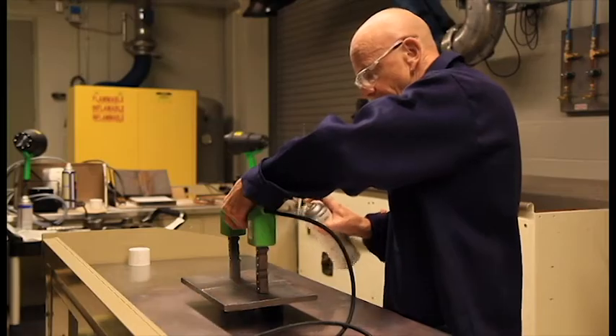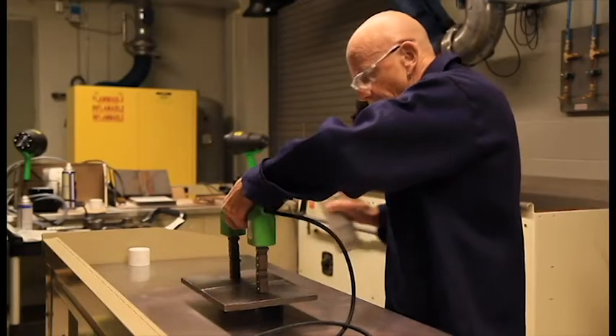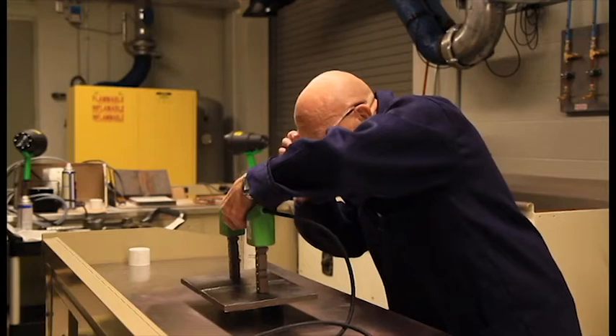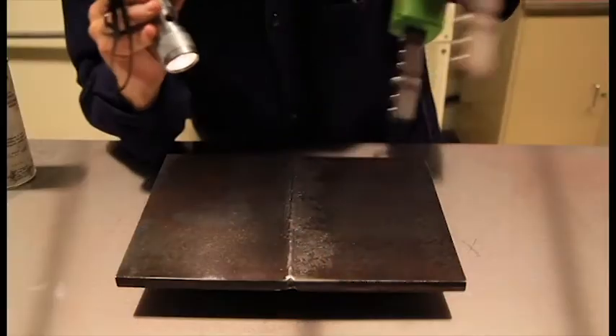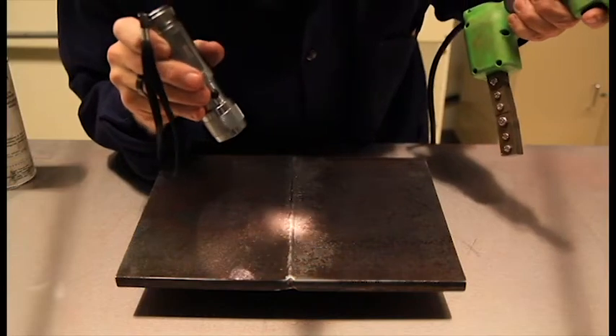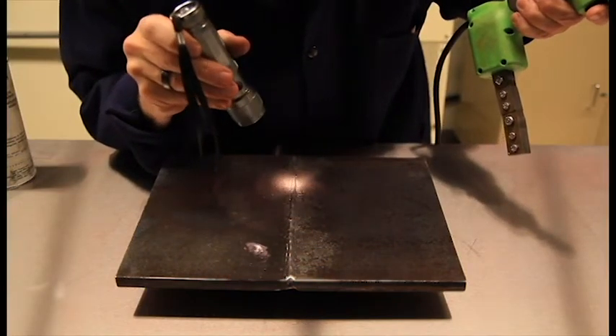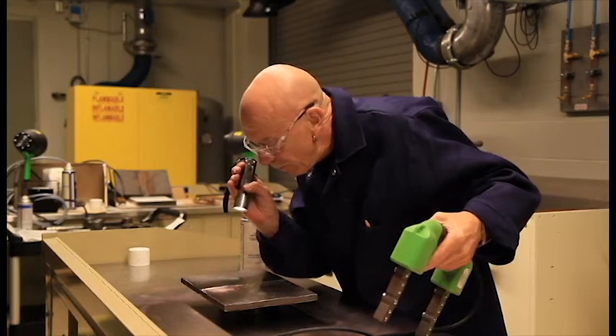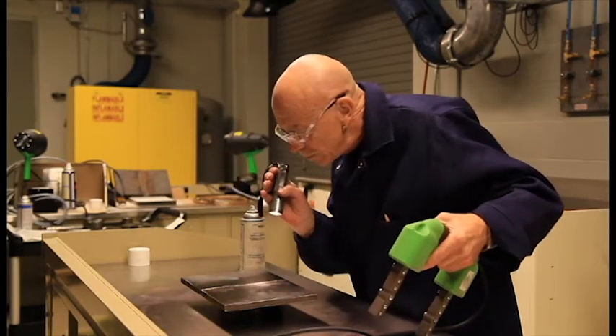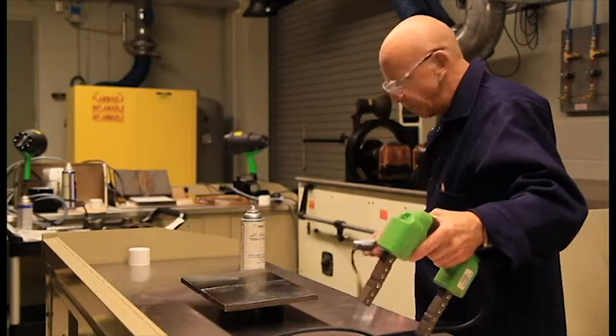Next, the magnetic particles suspended in a liquid are applied to the weld. In this process, there is no dwell time, and the surface between poles can be examined immediately. The magnetic particles will line up along any break in the magnetic field, such as a surface crack. Since the field is transverse to the weld, only indications lying in the longitudinal direction will be picked up.